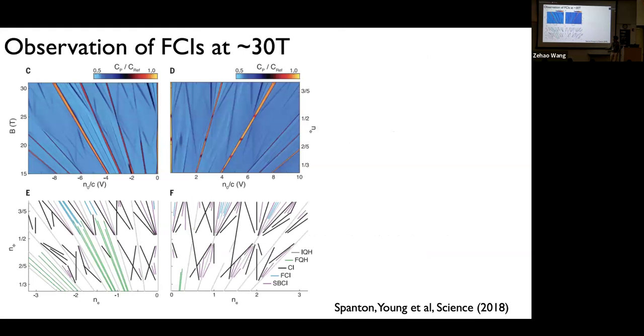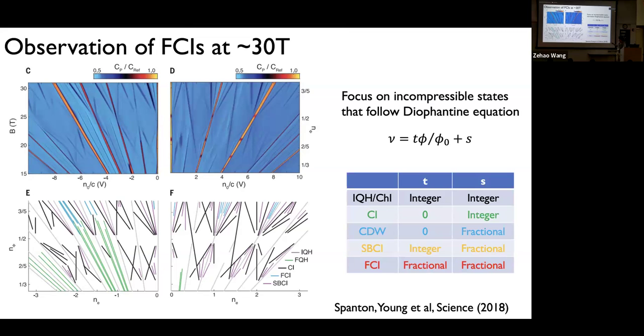And they did that, and this is the data they see. The top row is the data, hole-doped side, electron-doped side, and what you see is that there are a lot of linear trajectories. Some are stronger, some are fainter, and then what you can do, and that's what they did, is to analyze these linear trajectories. And the way to analyze this is looking at the slope and the intercept.